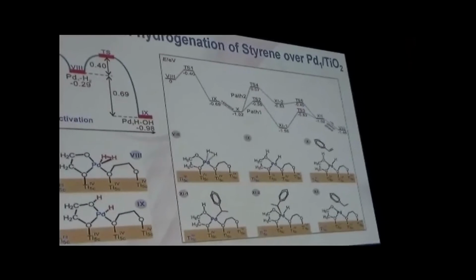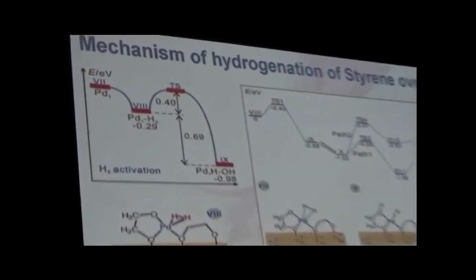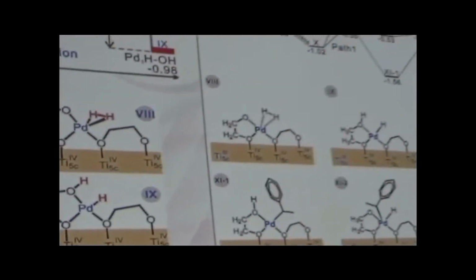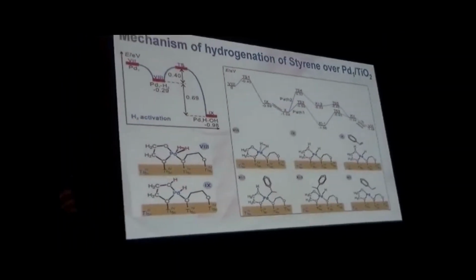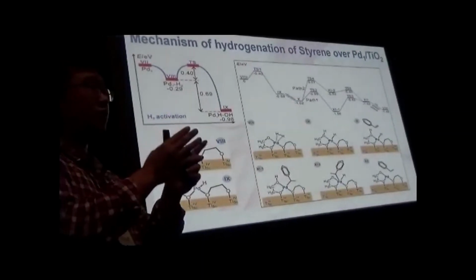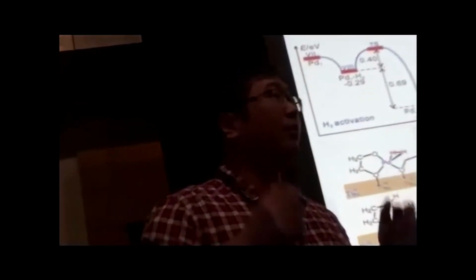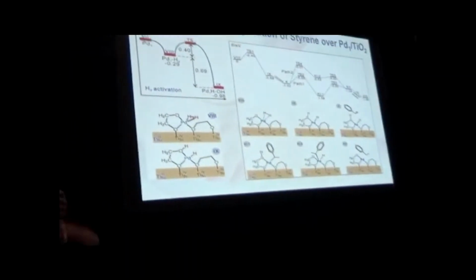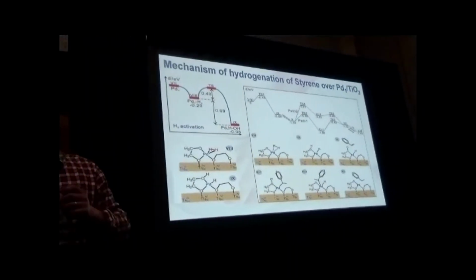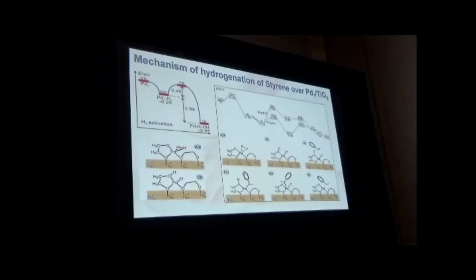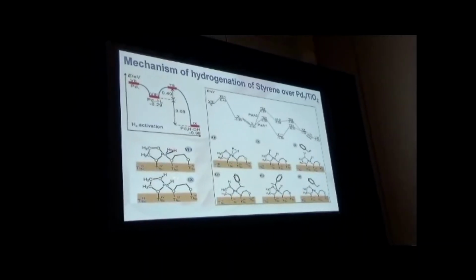Here's the hydrogenation mechanism. For hydrogenation on the single atom catalyst, as we know, hydrogen is usually dissociated on a metal-metal bond. It requires at least two metals. But in this case, we have a single atom system. So the hydrogen is dissociated on the palladium-oxygen bond. Again, it's heterolytic hydrogenation. We can generate one hydride and one proton. This is the hydrogenation for the C=C bond.